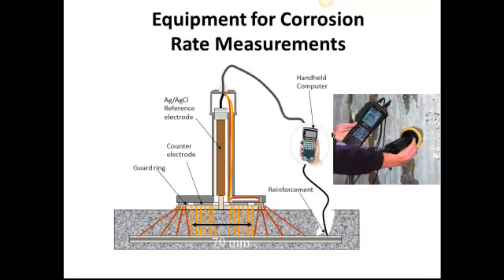Finally, this is a diagram demonstrating galvanostatic pulse measurement, which is a corrosion rate analysis. It is conducted by imposing a current into the concrete and measuring how this changes the voltage over time — that's polarization — and the measure gives you a corrosion rate. In combination with the likelihood of corrosion, this lets you determine very well where corrosion is likely to be occurring and where the most at-risk areas are. It's also a method that can be used in concrete structures that are very wet or saturated, where you would be unable to conduct normal half-cell potential testing. Thank you for your time.